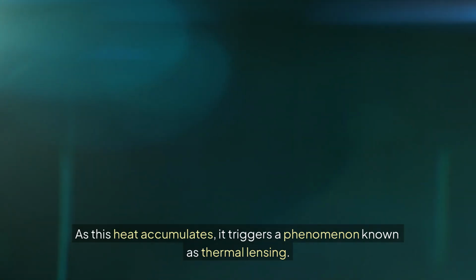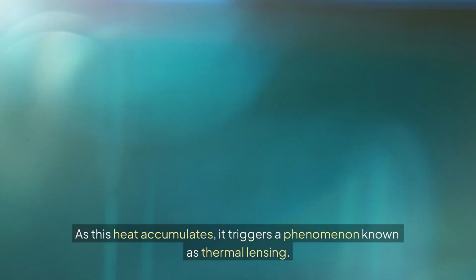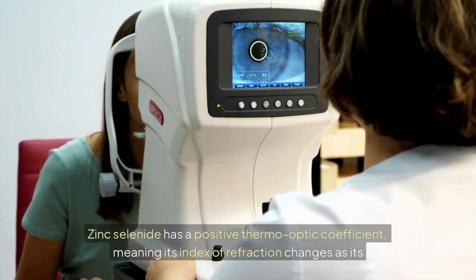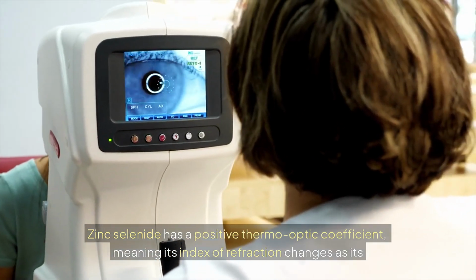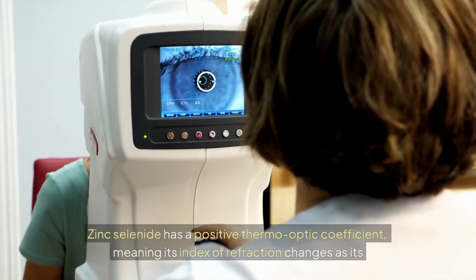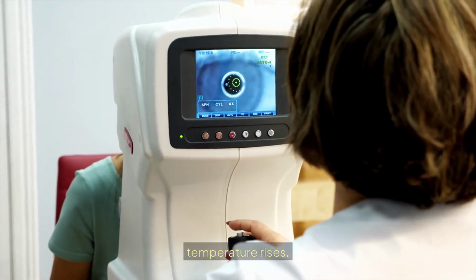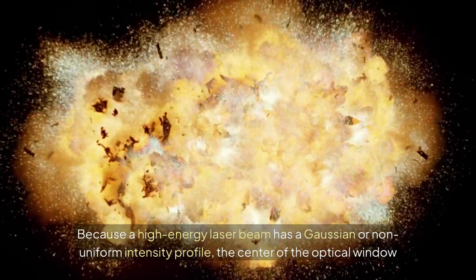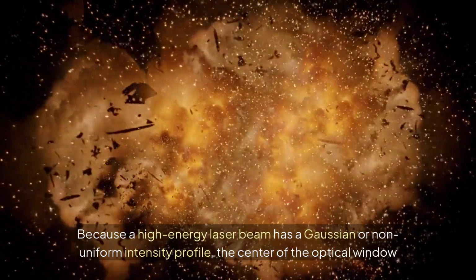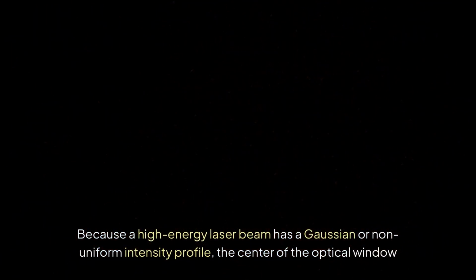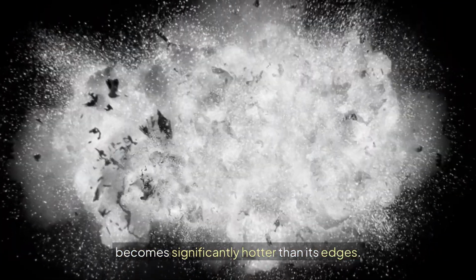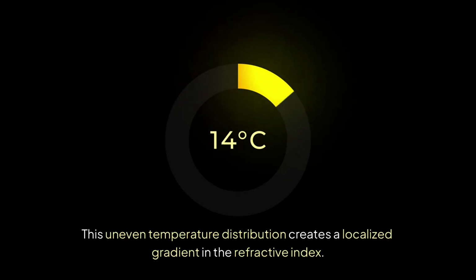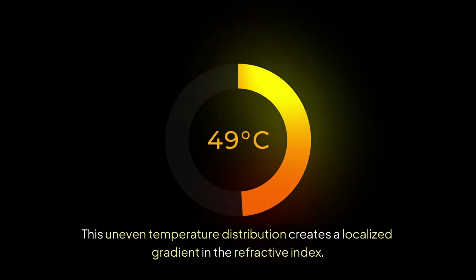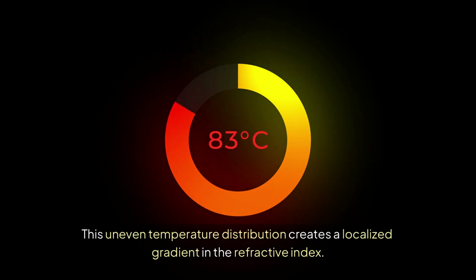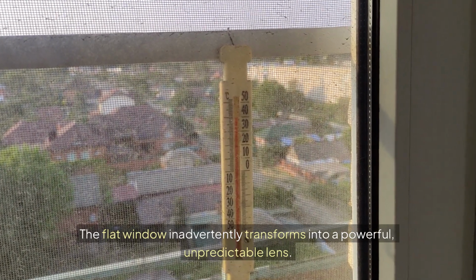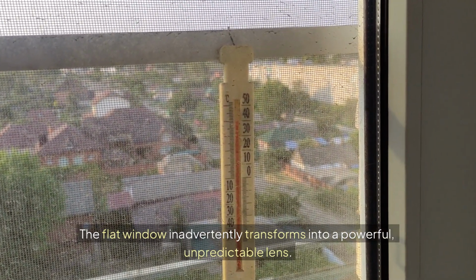As this heat accumulates, it triggers a phenomenon known as thermal lensing. Zinc selenide has a positive thermo-optic coefficient, meaning its index of refraction changes as its temperature rises. Because a high-energy laser beam has a Gaussian or non-uniform intensity profile, the center of the optical window becomes significantly hotter than its edges. This uneven temperature distribution creates a localized gradient in the refractive index. The flat window inadvertently transforms into a powerful, unpredictable lens.